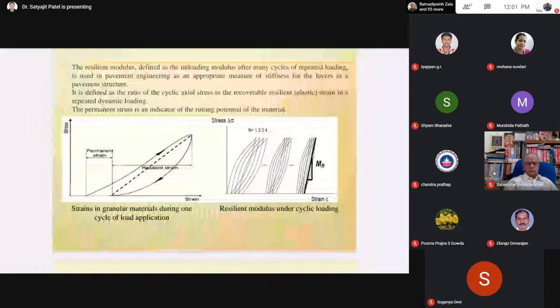When a number of repeated loads are applied, you will get the resilient modulus for each load cycle. So it is defined as the ratio of cyclic axial stress to the recoverable resilient strain in a repeated dynamic loading. And the permanent strain is an indicator of the rutting potential of the material. For a material, if the permanent deformation is more, its rutting potential will be more. So there is a major chance for that material to fail by rutting.